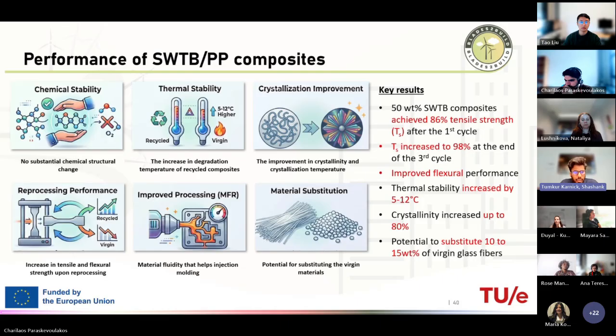And also, on the other hand, the material fluidity or the melt flow rate of the material also increased when we started increasing the amount of waste wind turbine blade. This particular material fluidity will also help in the injection molding of these specimens. For example, if we want to scale up these products, then this is the most important parameter which we also need to look into.